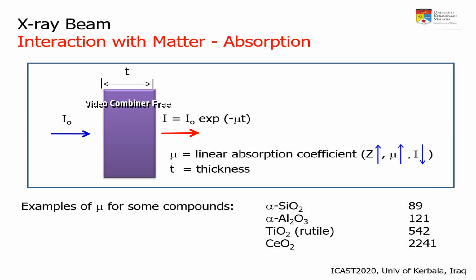Linear absorption coefficient, aka linear attenuation coefficient, describes the fraction of X-ray being absorbed per unit thickness of the absorber. Its value depends on the elemental composition of the material. An element with higher atomic number, Z, will have a higher value of linear absorption coefficient. Linear absorption coefficient values for a few compounds are shown in the slide.